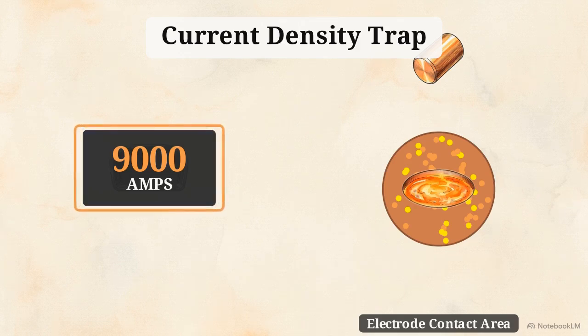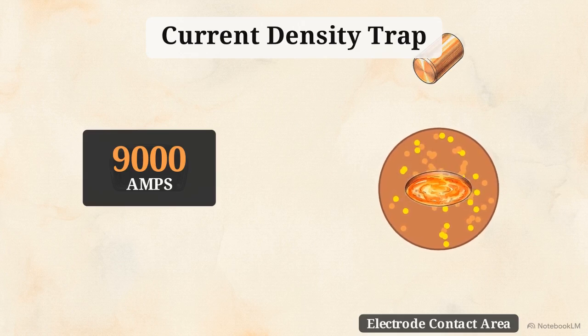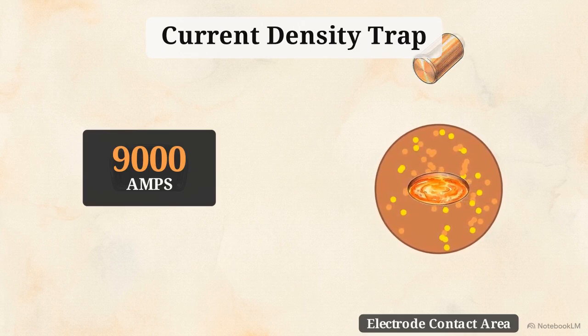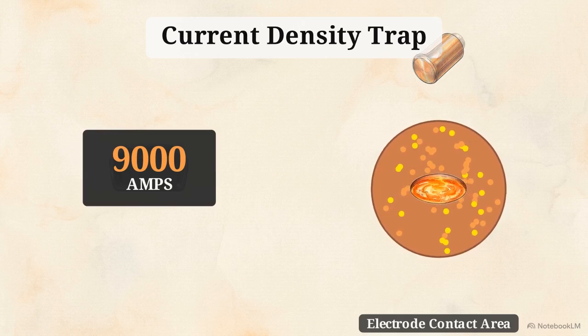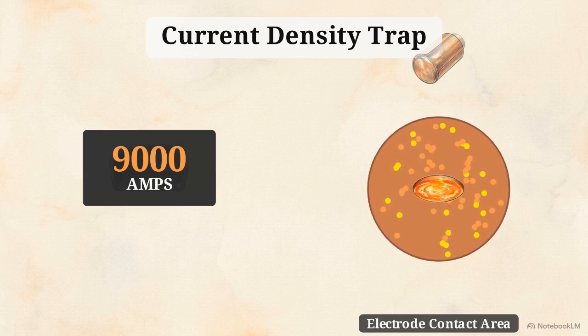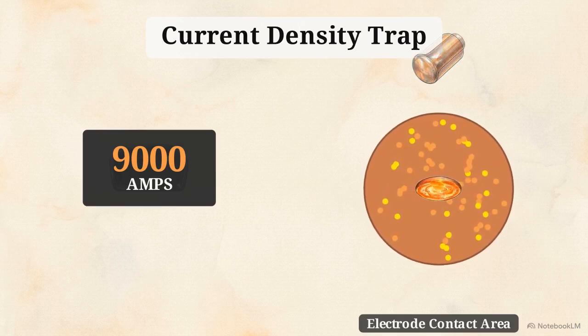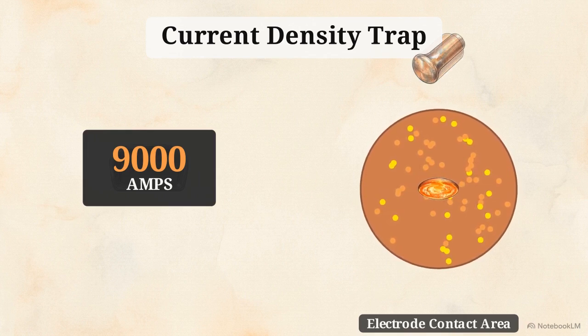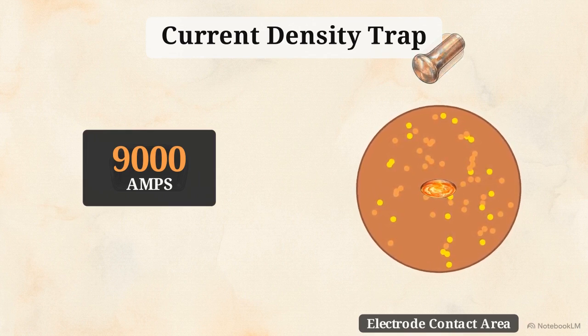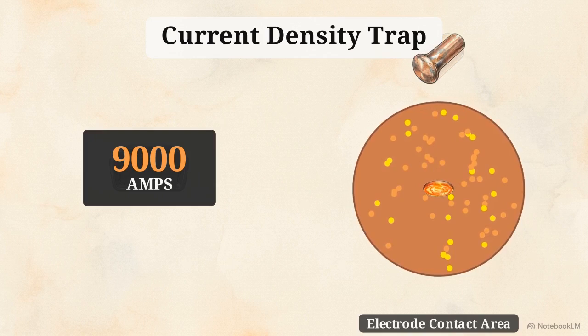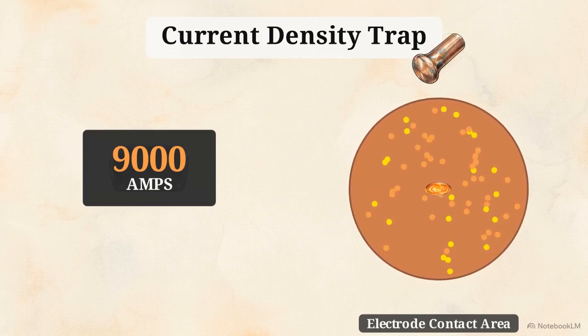Look at the left side. The machine is still outputting a locked 9,000 amps. But on the right, the tip face gradually expands in diameter. Because the surface area is increasing, those 9,000 amps are forced to spread out. The actual density of that heat at the center plummets. With less concentrated energy melting the metal, the resulting weld nugget steadily shrinks over the production run.